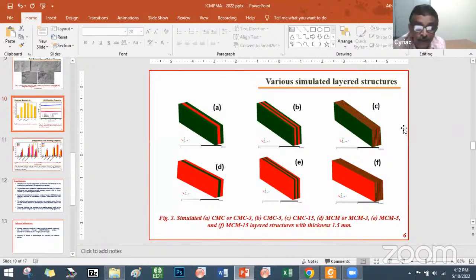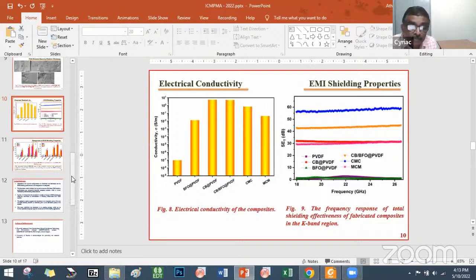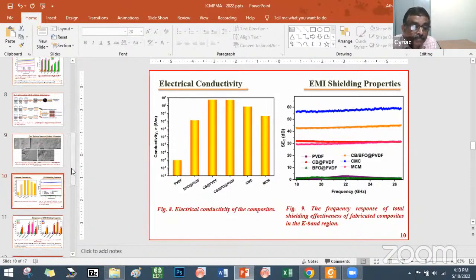Is there any optimum value of the thickness? Sir, for EMI shielding applications, actually we can go up to 2 millimeter. I think it is good to reduce it to 2 millimeter only. There are reports that suggest you can go beyond 2 millimeter, but it is not commercially feasible. If it is less than 2 millimeter, that's good economically. If you want to give your material for industrial applications, the thickness should be restricted as much as possible. It's good to reduce it to less than 2 millimeter.